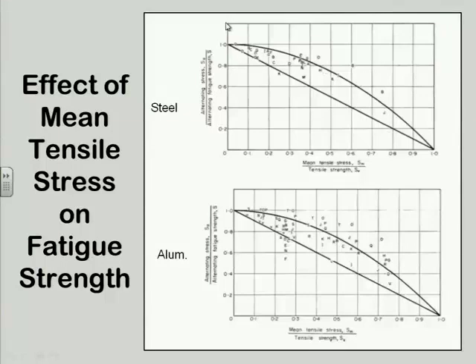And that's bad enough, because we've already discovered that your allowable strength, the usable strength of a material, is of the order of a fourth to a third of its advertised value statically, the ultimate tensile strength rather. And when we get through with all the factors and whatnot for endurance strength, we find we're down around 25 to 30% of the number we started with. That case is on the vertical axis here. This is the alternating stress axis, and this is the mean stress axis.